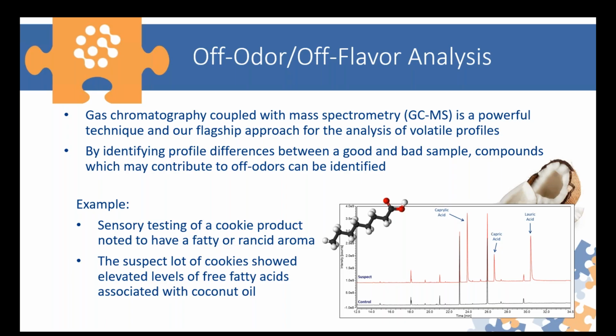What we're doing here is looking for the differences in these profiles. In this case, we saw the presence of additional peaks resulting from rancidity, but the reverse could be true as well. For example, another cause of an off flavor may be that during production, an ingredient was missed, a flavoring was missed, such as vanillin. In that case, we could see that the suspect sample is missing vanillin when it is present in the control.